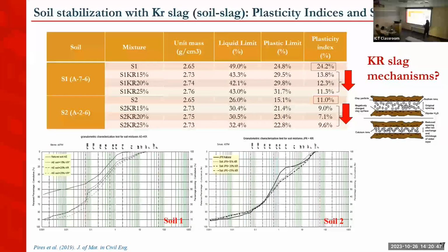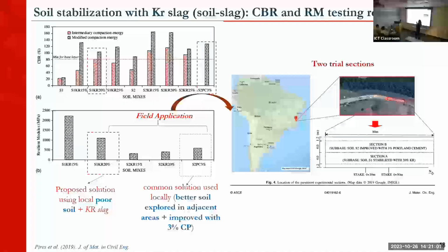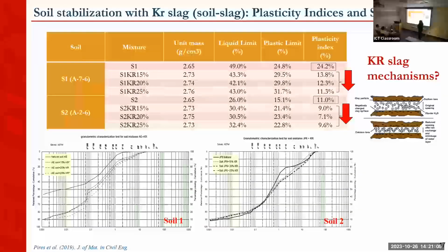So one thing that we started to hypothesize is that there might be some cation exchange happening. And we are reducing the double diffuse layer that is present in clay soils. Clay minerals are interacting with cations from the KR slag. And that may be the reason that we are having this reduction in the plasticity index.